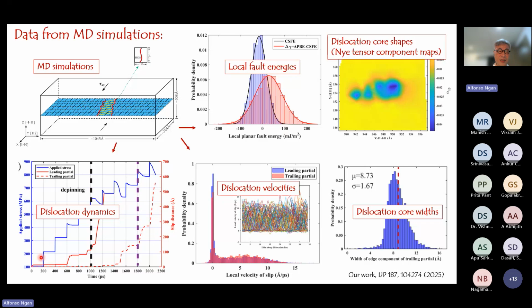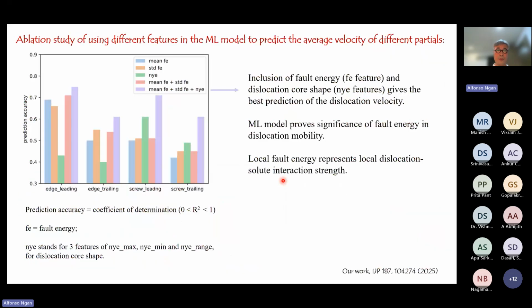Or from the stick-slip motion of the dislocation, you can back out, let's say, the velocity, which is shown in here. The velocity probability profile is shown in here. So you can generate a lot of data. So as I said previously, we want to understand which of these factors are more dominating in controlling the dislocation mobility, reflected in terms of the dislocation velocity.